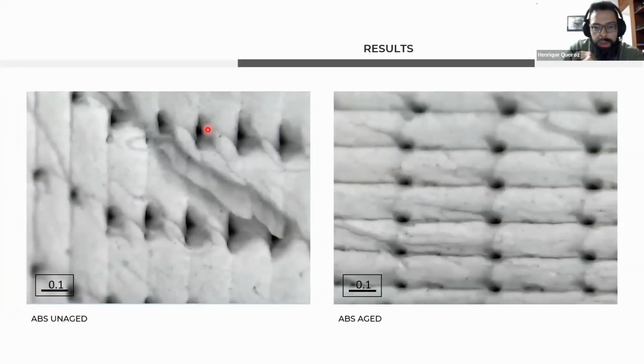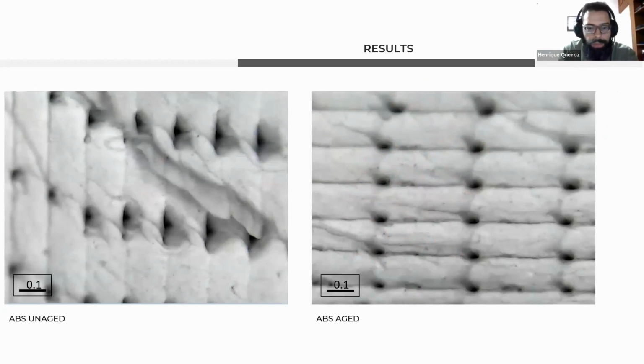Now, we see the same fractures for the ABS specimens here, but of course, we do not see this significant debonding. We can still see, for instance, here, this is the unaged ABS. And there's good bonding between the layers, but when we look at the aged, we can also see small cracks between the layers. Now, the interesting thing here is that the cracks are, let's say, more homogenized. You see them almost between each layer. While in PLA, you have like two layers that completely debonded. And so this acts to sort of balance out a little bit, right? You don't have a significant debonding, but you have a lot of small debondings. And so it deteriorates, but it deteriorates slower, right, at a lower rate.